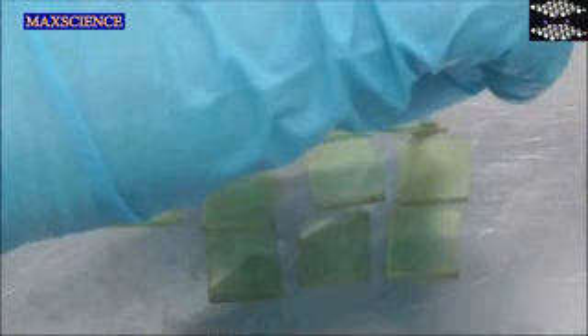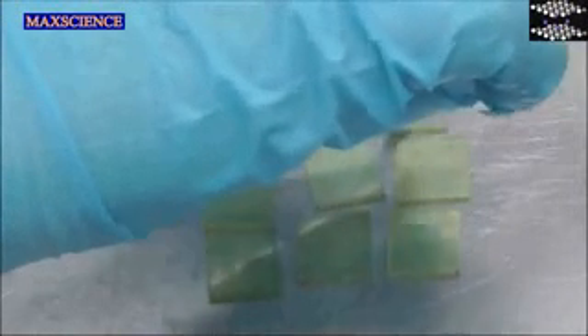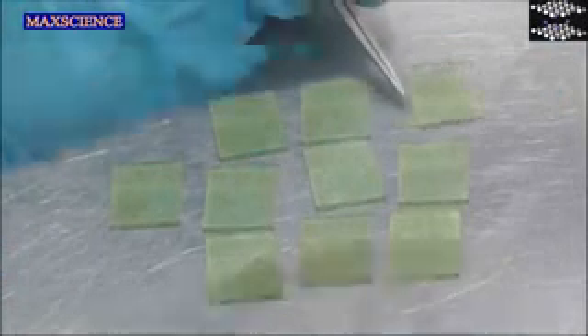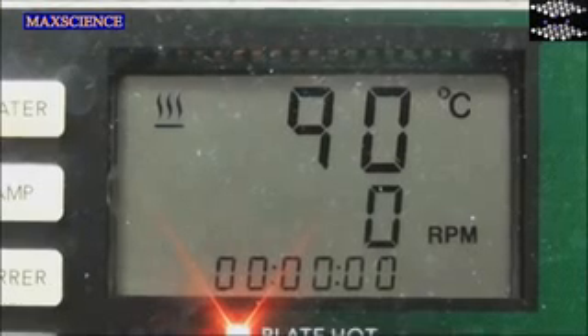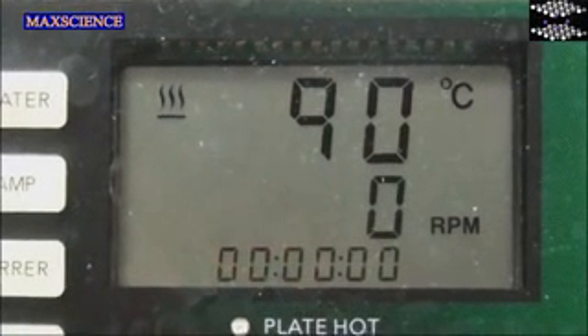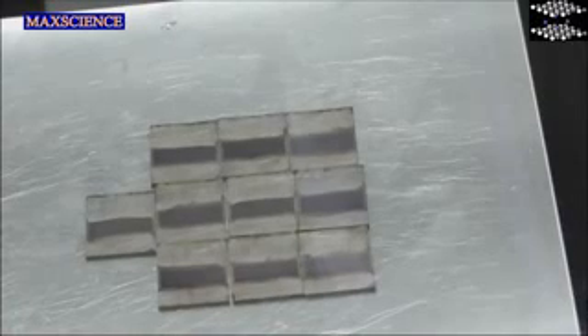After all substrates have been coated, use a dry, clean room swab and wipe the place where the cathode contact will go. This wiping removes the perovskite precursor from the surface. Now place the substrates back onto the hot plate and anneal for a further 90 to 120 minutes to fully convert the mixed halide perovskite precursor. After this time, all films should have turned from yellow to grey-brown.